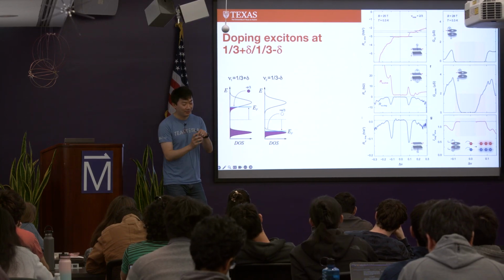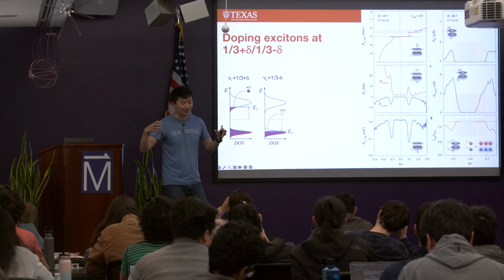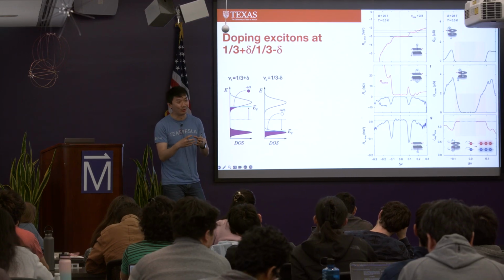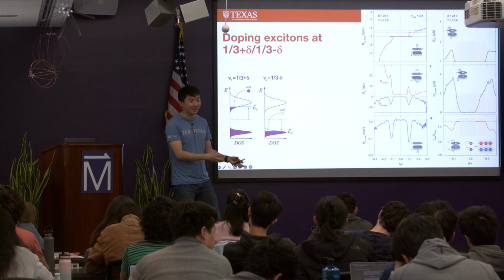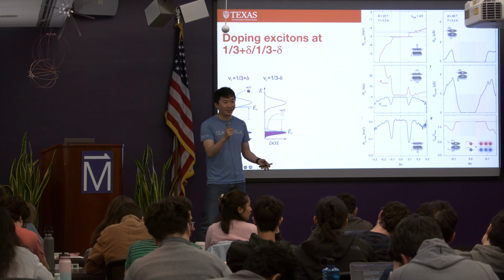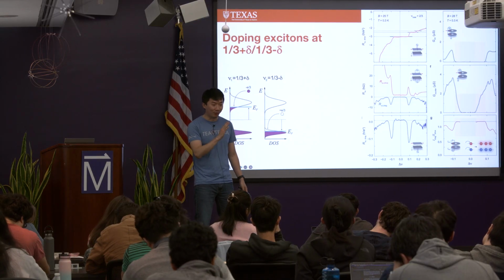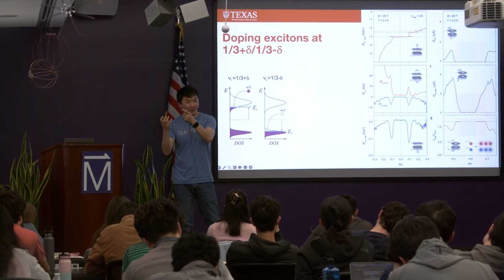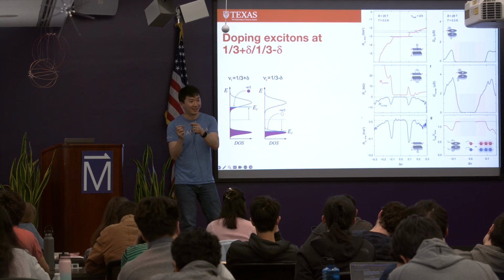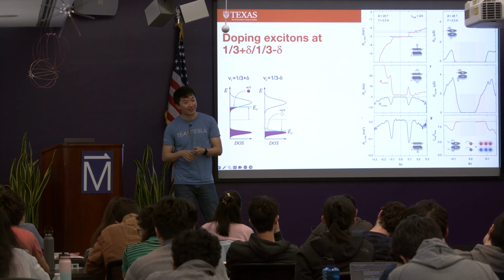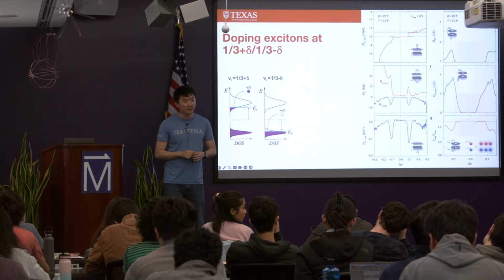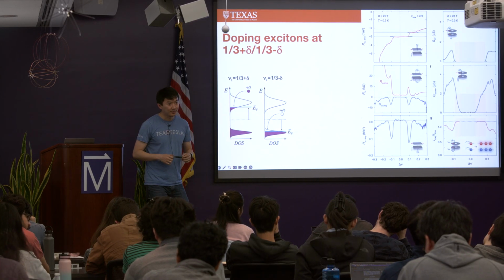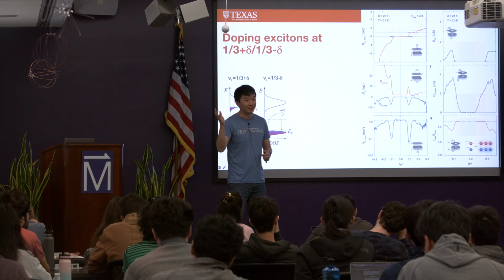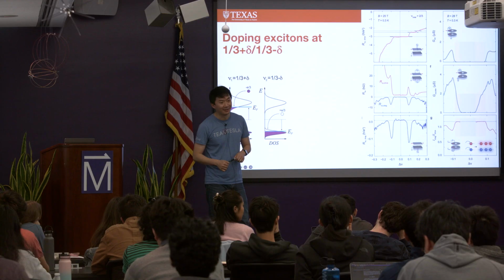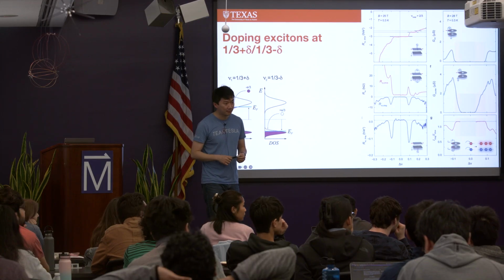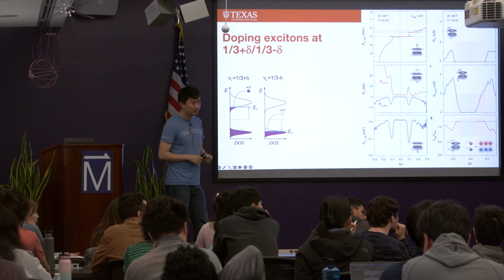My understanding is that the exciton condenses when you pair a few fractional excitons together to form a bosonic exciton, right? So the condensate is still a bosonic condensate, but the only difference is in the normal state. When you go through TC, right, the quasi-particle you get is, instead of a bosonic exciton, they split back into the anyonic exciton. The condensate might look just like an ordinary exciton with one electron and one hole. Right. But the parent state is a fractional exciton. Right. That's my understanding.